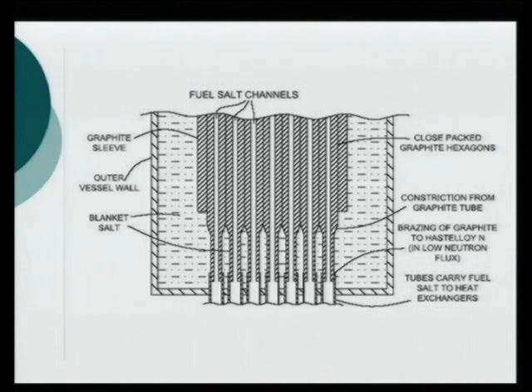What we do here is, if those graphite elements are, say, 15, 20 centimeters wide, we constrict those down. So now fuel blanket salt can get between those pipes, okay? And that basically kills criticality, and it'll absorb all those neutrons. So where we contact from graphite to Hastelloy, which Oak Ridge looked at before, brazing to the tubes, that's done outside the flux, okay? So you might be saying, oh, well, that's back to the plumbing problems. But we have no blanket salt between those pipes, so we don't care if they're expanding and contracting. It's not really going to change the overall criticality of things or the overall ratio of things. So just one of the suggestions here.